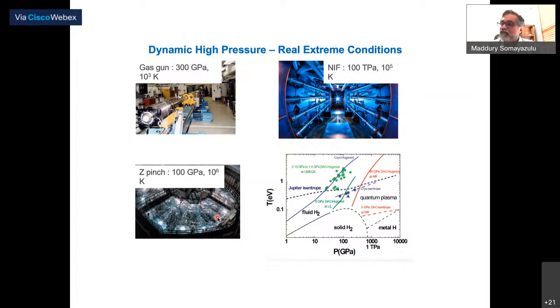What about dynamic pressures? There are various ways of doing dynamic pressures. It turns out that in dynamic pressures, your range of pressures and temperatures are much larger. And of course, consequently, the time over which you achieve these is also smaller. But I just wanted to give you a flavor of that. There are laboratory-based techniques like the gas gun, and you can go all the way up to the NIF, where you can go up to hundreds of TPa, which is about 100 times what you can get from a diamond anvil cell, and about 10 power 5 Kelvin, which is about 100 times again the kind of temperatures you can get in a diamond anvil cell.